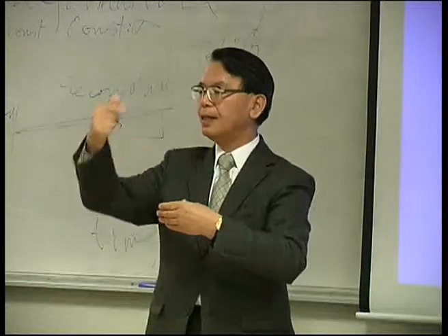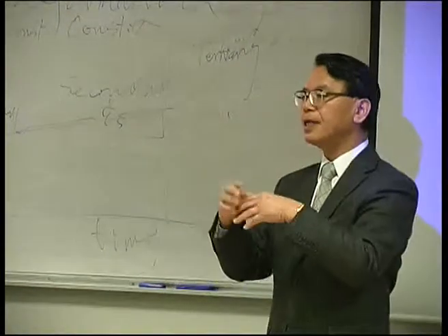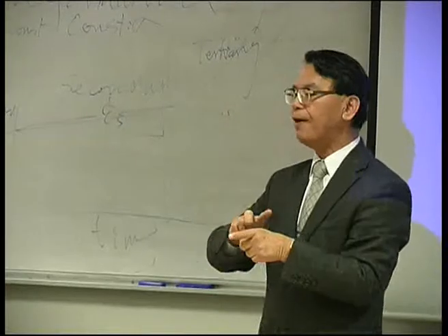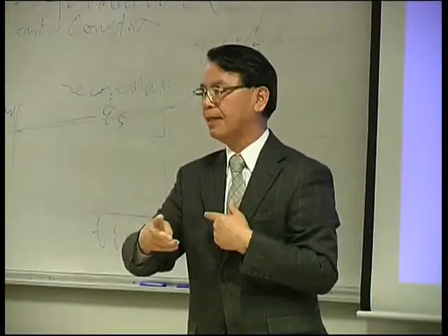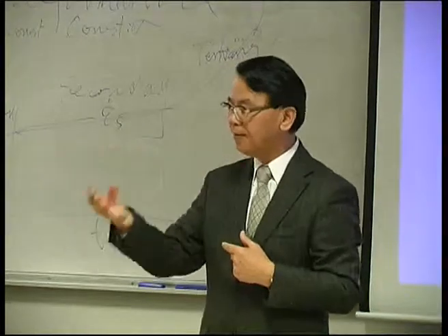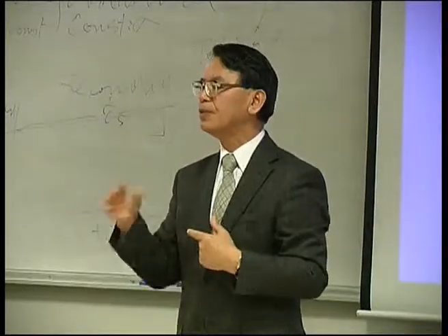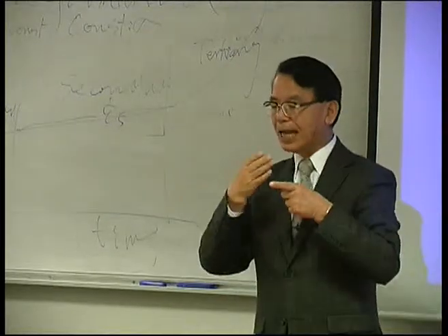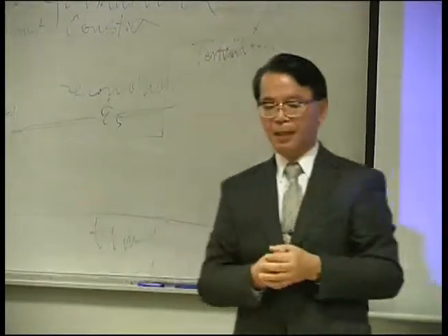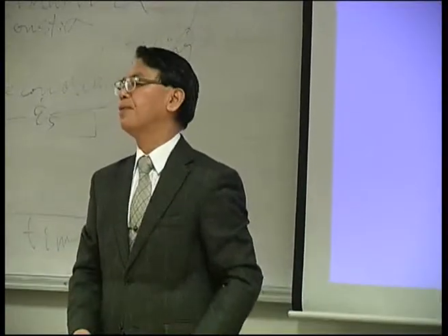By increasing the magnetic moment by alloying an element like cobalt, the elastic modulus can change, as I already mentioned. That directly affects the dislocation, the Peierls-Nabarro force, even that very elementary process of dislocation motion. Also, diffusion can be affected. The interaction of dislocation motion and the domain wall is a rather new topic. Recently, we have directly observed grain boundary and domain wall by Lorentz microscopy or other techniques. But anyway, such basic design is needed to solve this problem.